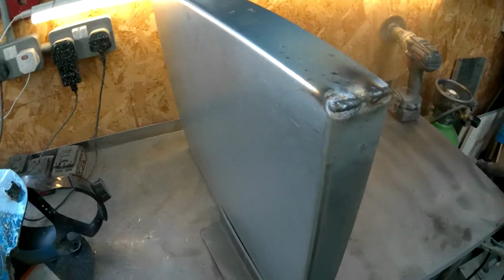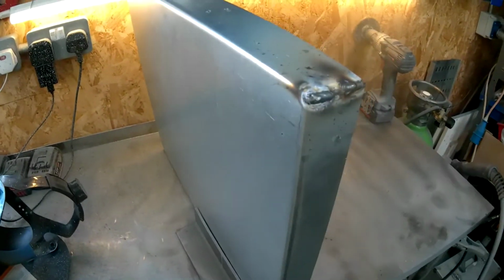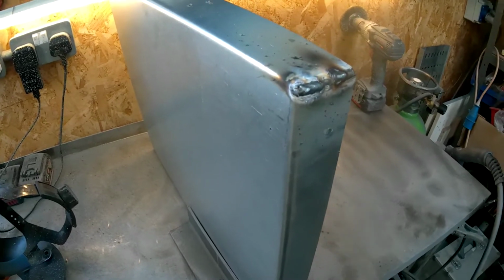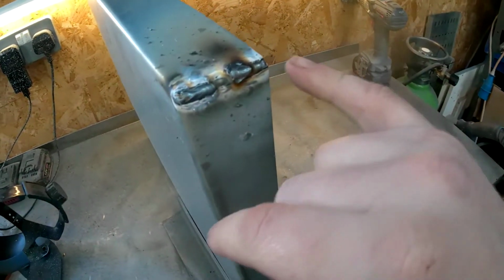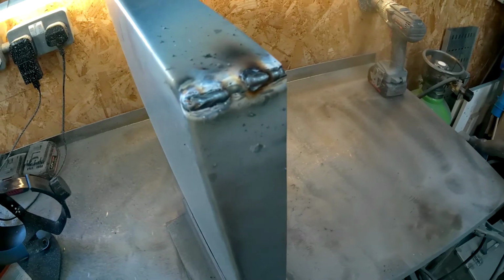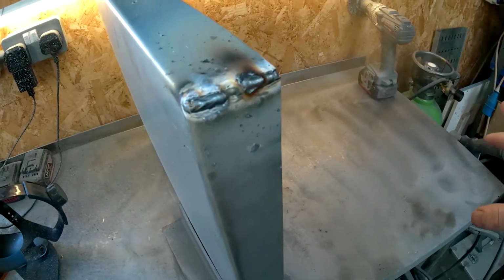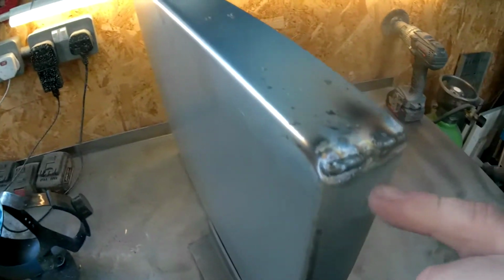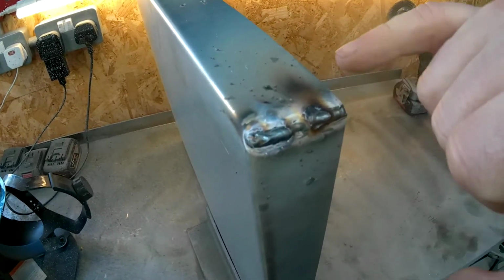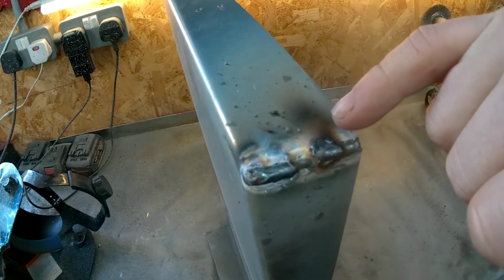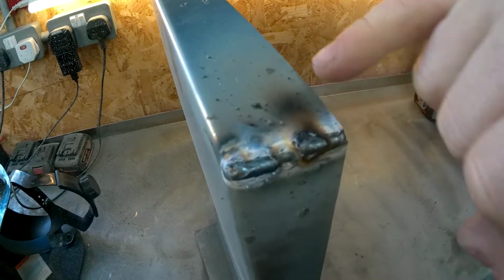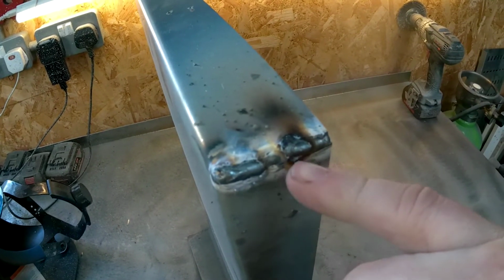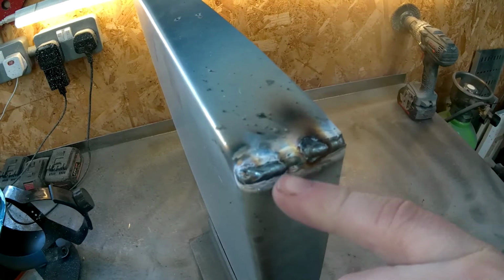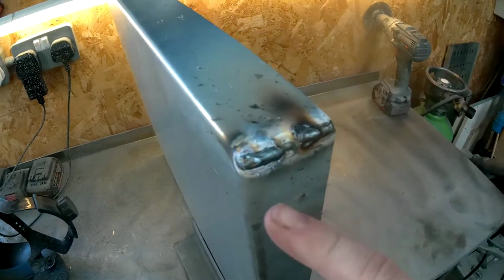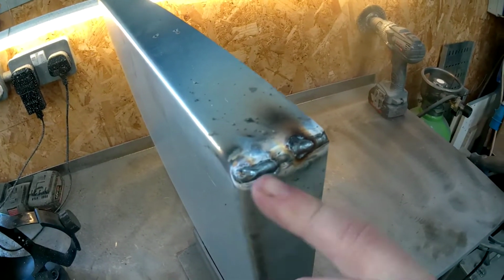Right, just to show you the difference that changing settings on the gas can make. This weld I did on the setting that I started with, which was about 10 litres per minute, and you can see here we've got a blowout of impurities. That's what that black stain is. I just went through there, and the weld is not particularly clean, so I have to clean that one up and redo some bits.